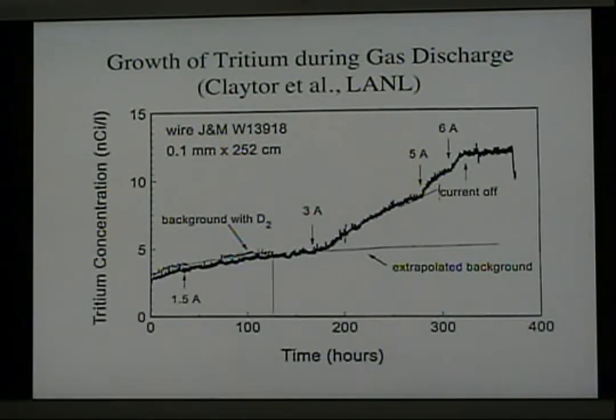Tritium can also be made by gas discharge. In this study, Tom Claytor at the Los Alamos National Laboratory caused a discharge to form between two palladium electrodes in deuterium. The gas was circulated within the apparatus, and the tritium was detected using a device that was sensitive to the beta decay, the current generated by the beta decay. This technique was checked against the more conventional method by converting the deuterium to heavy water and then placing it in a scintillation detector. The two gave exactly the same values for tritium, and so you can be confident that these measurements are accurate.